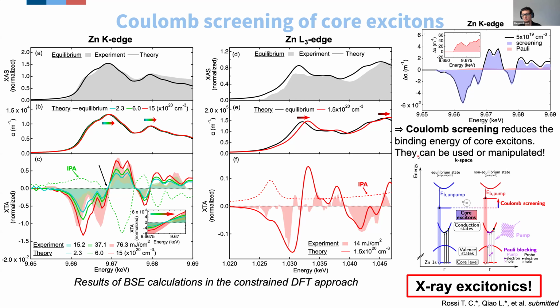And this is what we needed to, let's say, start the field of X-ray excitonics, because this is essentially one way to manipulate them. So I put a figure here showing how this is actually working: we have a pump pulse that excites carriers between two bands, the valence band and the conduction band. And the effect it has on the X-ray absorption spectrum is really to just renormalize the binding energy of core excitons, leading to a blue shift. So this is very nice, and I think it's a novel idea and should in principle be happening in any semiconductor material in the excited state, basically. And it should be used to actually infer the presence of excited carriers in semiconductors, for instance.